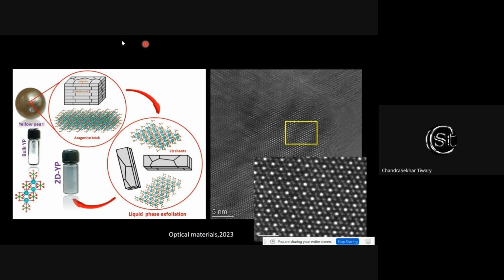But pearl is another interesting layered material where aragonite crystalline structures are separated by organic molecules. We take this pearl, crush it, and then exfoliate it. Once you exfoliate it, it makes a nice suspension of 2D material. The transmission electron microscopy shown here clearly shows the crystallinity is retained with a very thin, 1 or 2 layer thickness.